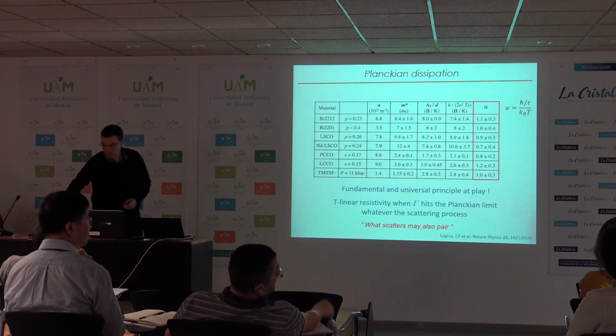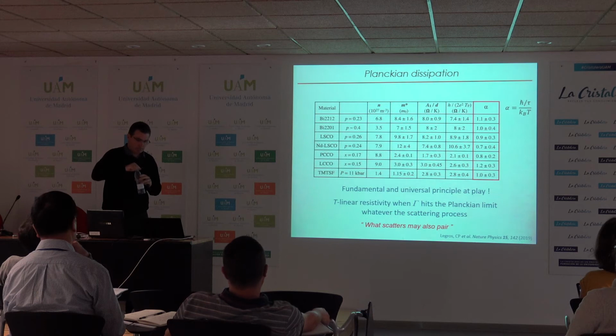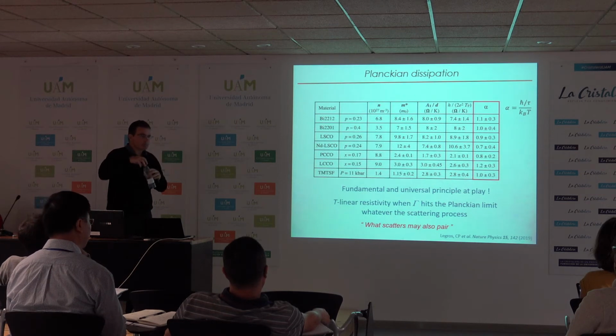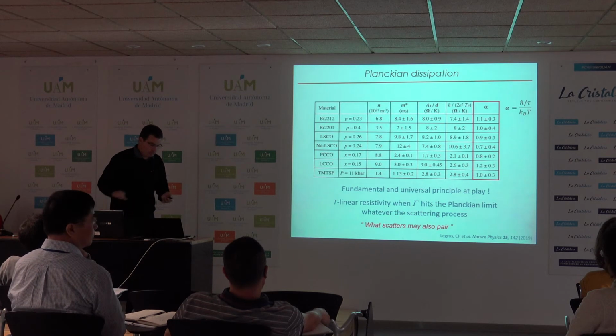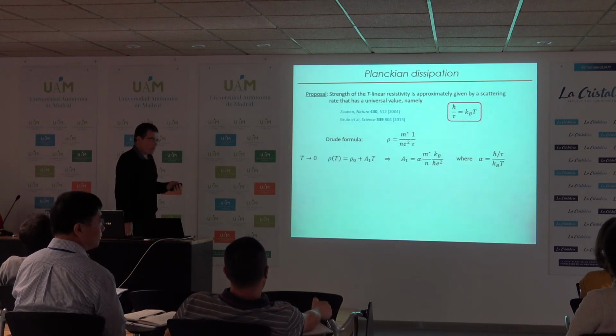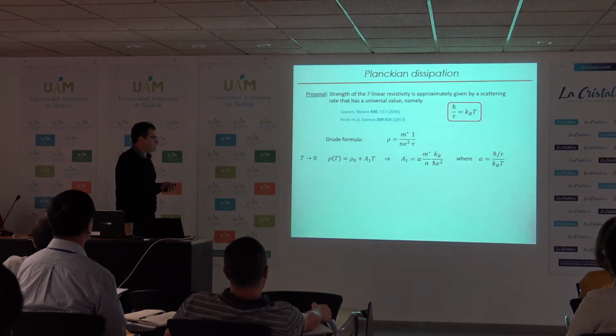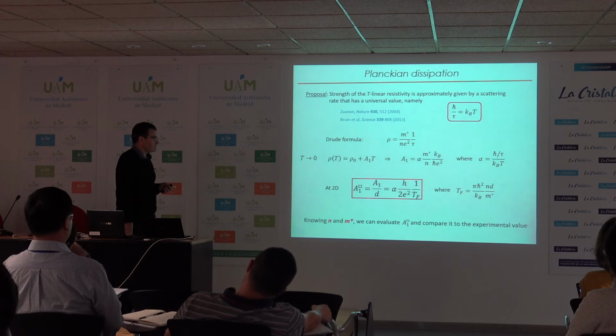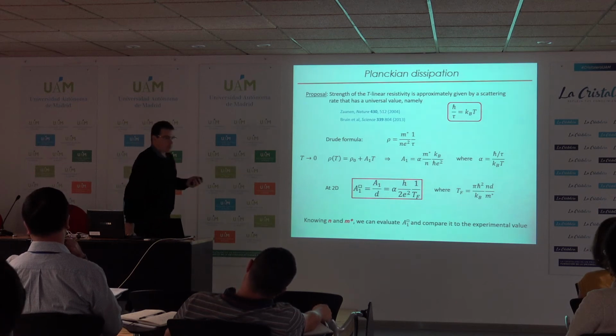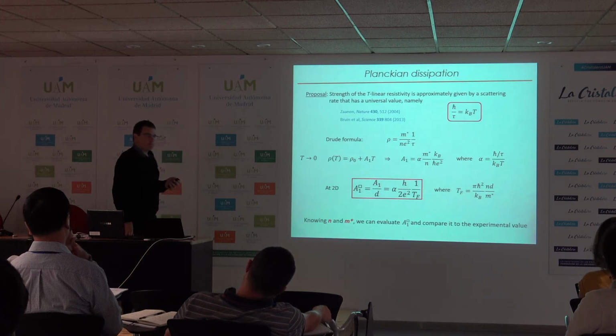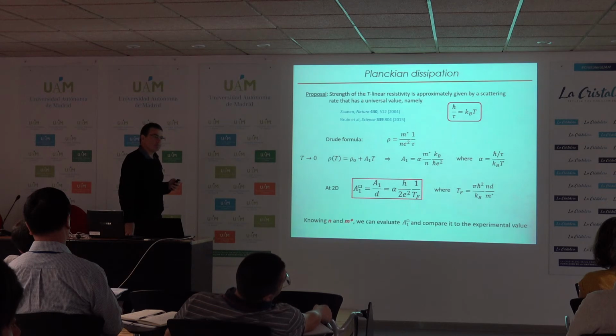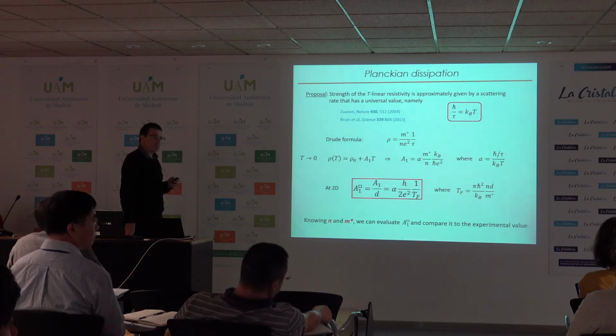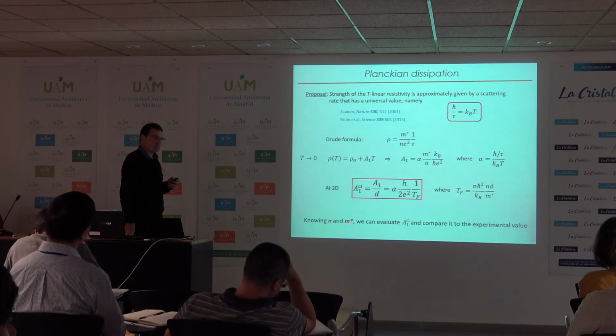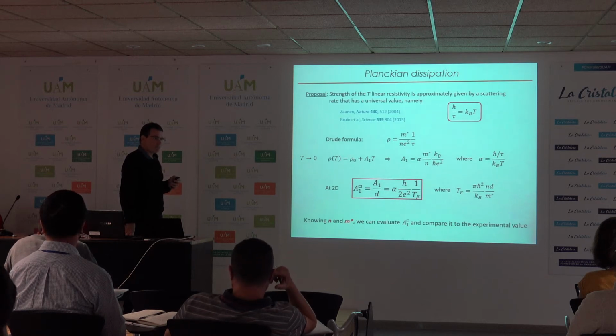Cyril? Yeah? In your estimate, you would reach the Mott-Ioffe-Regel limit when the temperature is comparable to the Fermi temperature. So the sheet resistance, or conductance, would be e squared over h when T equals T_F. Should I take this T_F literally as the Fermi temperature of that system? That's what we have done, actually. But we do know that experimentally the resistivity reaches the Mott-Ioffe-Regel limit, or even surpasses it. But I always thought that the Fermi energies in these systems are larger than 200 Kelvin. Yeah, so that's why I'm asking whether this is a concept.